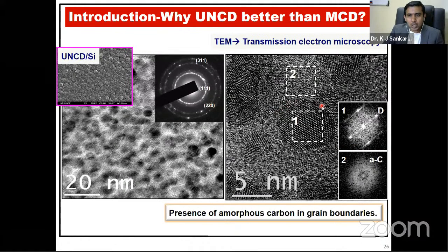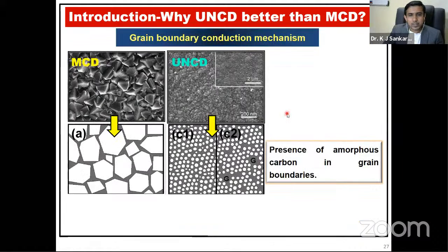Very small, ultra nano sized diamond grains, and in the grain boundaries between these two diamond grains we can see amorphous carbon phases. So these amorphous carbon phases exist between these two diamond grains. This is a diamond grain and these are the grain boundaries present in the UNCD films. The presence of amorphous carbon in the grain boundaries gives a very easy grain boundary conduction mechanism, because the amorphous carbon in the grain boundaries helps the electron transport.